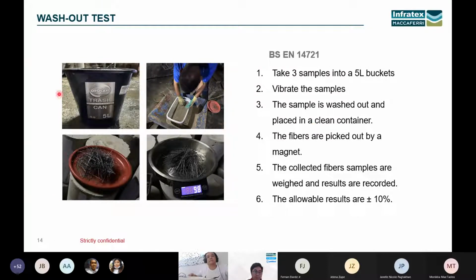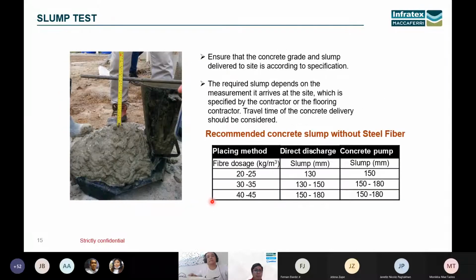For this specific test, the dosage of steel fiber is 20 kg per cubic meter. So theoretically, the amount of steel fiber for our 5-liter bucket is 100 grams. After the testing, we recorded a weight of 98 grams. That indicates that the steel fibers are uniformly distributed within the concrete mix.